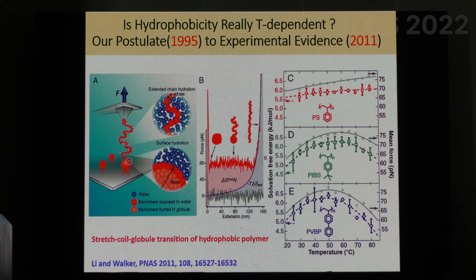And so here is an atomic force microscope where you take a large polymer chain, which has these hydrophilic, hydrophobic interactions. You attach an end of the polymer chain to a nano tip, and then you pull this nanotip away from the polymer, right? So the polymer is grafted on this surface, and then you're pulling this tip out, and what you can measure is the force required to pull out. And that force is actually because the polymer has to have, of course, an elastic force on the polymer, but it also has to overcome the interactions with the surrounding solvent.